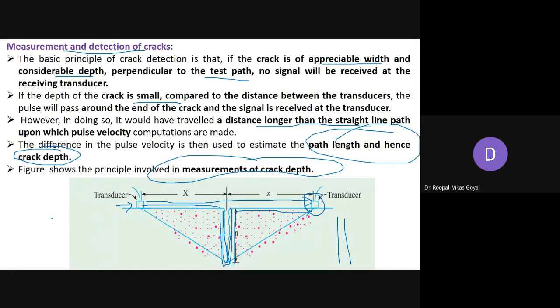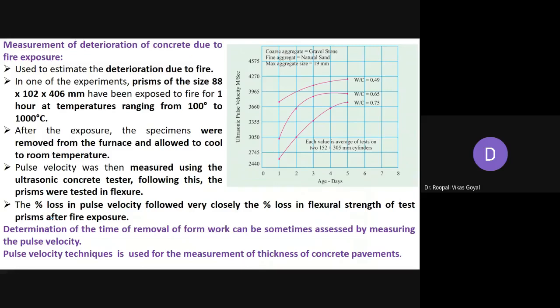Also, you can measure the deterioration of the concrete due to fire exposure. For that, some experiment was done to check ki fire mein kitna deterioration hota hai concrete ka. That was done with the help of a prism of size 88 by 102 by 406 mm, which was exposed to fire for 1 hour at temperatures ranging from 100 to 1000 degrees. After exposure to such high temperature, the specimen was removed from the furnace and allowed to cool down. So room temperature pe cool down kiya and pulse velocity measure kiya.